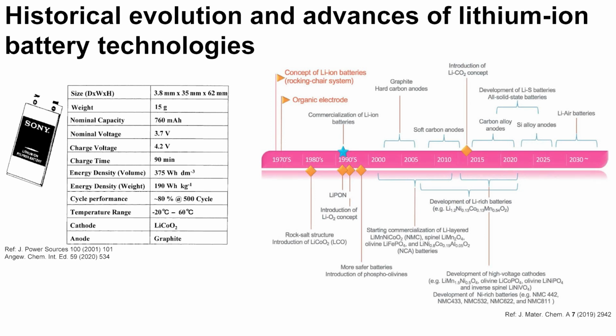Whittingham and colleagues at Exxon noticed that metal chalcogenides, MX2, possess a layered structure and available space to store Li-ions. They demonstrated that titanium disulfide, TiS2, can chemically intercalate Li-ions in its full stoichiometric range, showing minimized lattice expansion. In 1973 and 1974, Whittingham applied TiS2 as the cathode for Li-ion batteries and eventually exhibited a 2.5V battery cell in 1976. However, the formation of lithium dendrites, leading to short-circuiting, limits the application of Li-ion batteries.